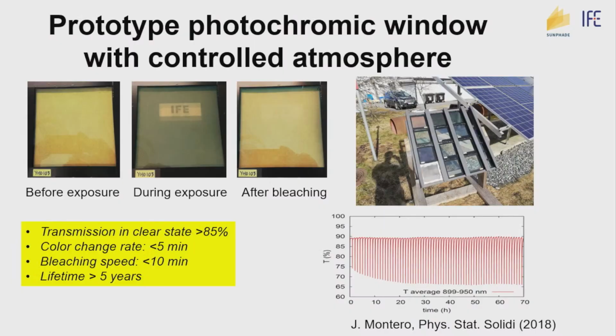And then after cyclic testing, the transmittance in the clear state and in the dark state was reducing, unfortunately, but then we found a way how to mitigate it. Then we made this type of prototype windows and we started testing in outdoor conditions. Now we have a demo house, a mini demonstration house. And this is now what during cyclic testing we achieved: constant transmittance spectra. And yeah.